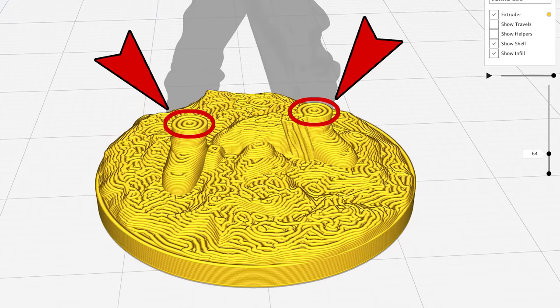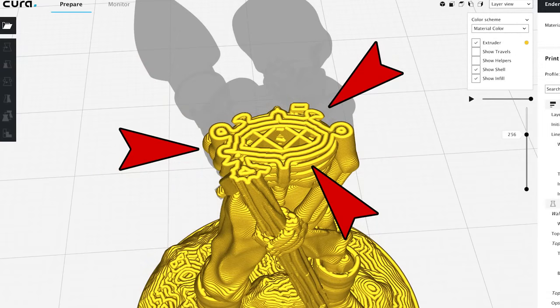In this image, I'm showing the ankle area. Again, it's just barely big enough for the three shells, no infill. So adding 100% infill will not gain you anything here. And these are the weak point of the miniatures. If anything's going to break, it's going to be these thinner areas. So the 100% infill doesn't gain you anything as far as strength for the key areas or the weak areas. And it will work against you on other parts of it with stringing and the overages on the sides. If you look at the torso here, same thing. Three shells is more than sufficient to give you a strong miniature. You don't need 100% infill. In this case, the arms are only printing with two shells on each side. They aren't even big enough for the three, let alone having 100% infill.